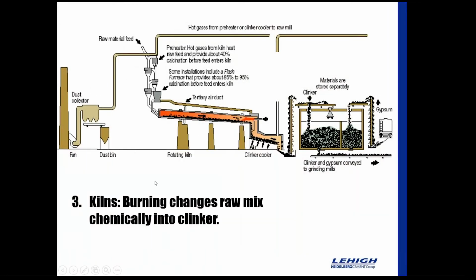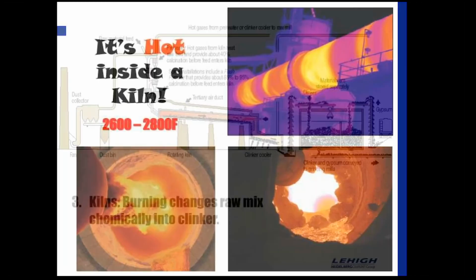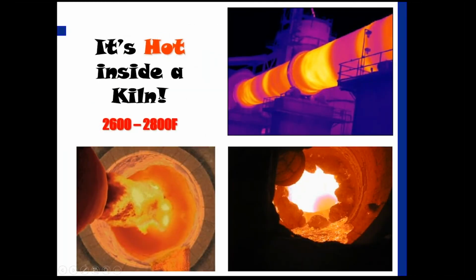And so once the material goes into the kiln, that's where things really start to change. Burning changes that fine gray powder chemically into clinker. And clinker is kind of, we'll talk about what that is. Inside the kiln, it's hot, and it's going to be anywhere from 2,600 to 2,800 degrees Fahrenheit. In the bottom right picture here, you can see that our fine gray powder almost starts to look like lava now as it kind of comes down through there.